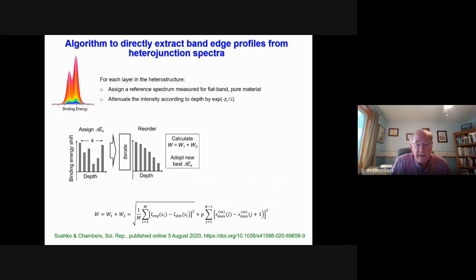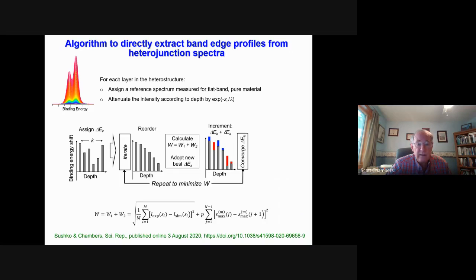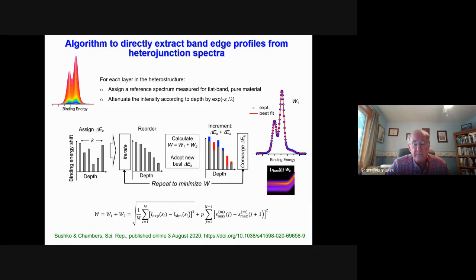And so we vary P in a systematic way, which is the weighting factor on W2. We vary that in a systematic way so that we can tune for smoothness in the potential without losing the quality of our fit. So we do the fit, and then we jiggle the binding energies again, and we resort, and we recompute W, and we keep doing that again and again and again until we minimize the total cost function. What we end up with then is a family of spectra, which when summed gives an excellent fit to the experimental spectrum, like that. And from that binding energy profile, we can extract then a band edge profile by just offsetting it by a constant energy difference between the core and the top of the valence band to get the band edge profile.